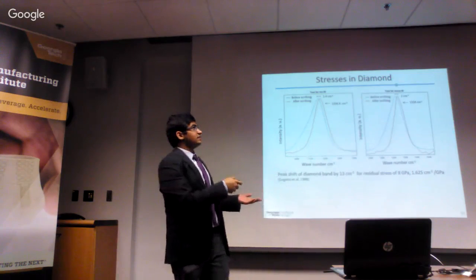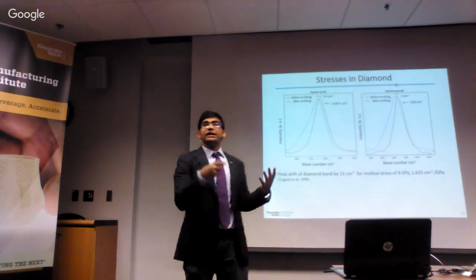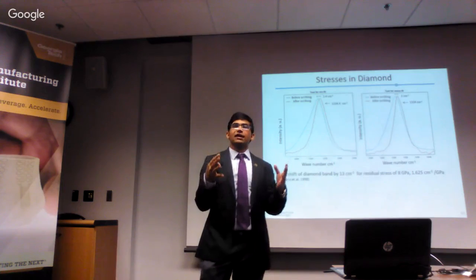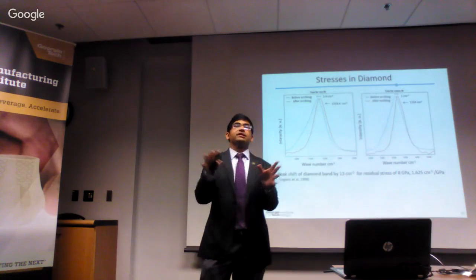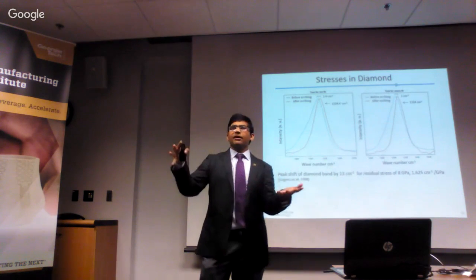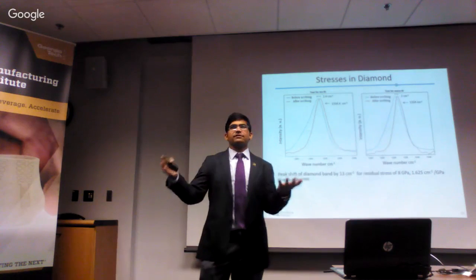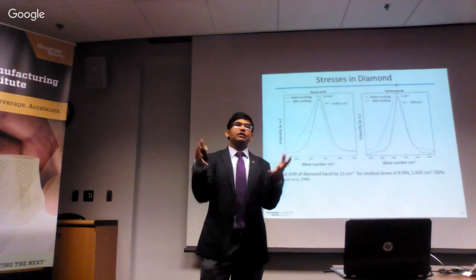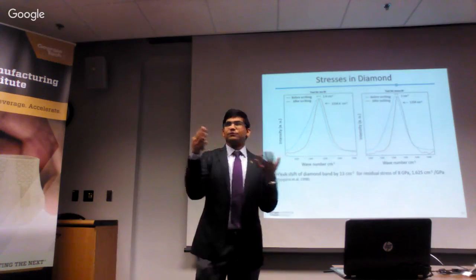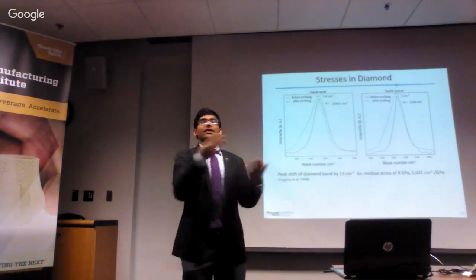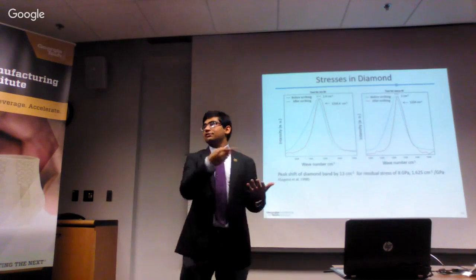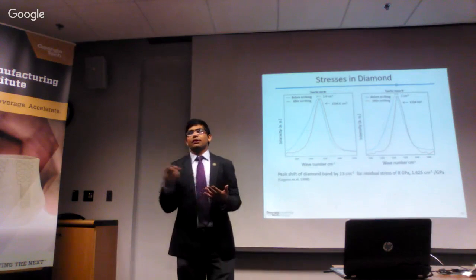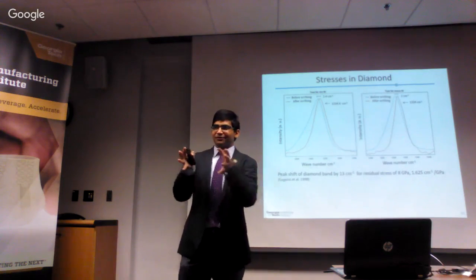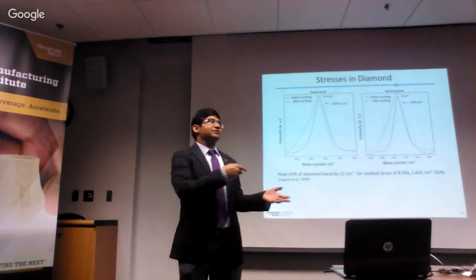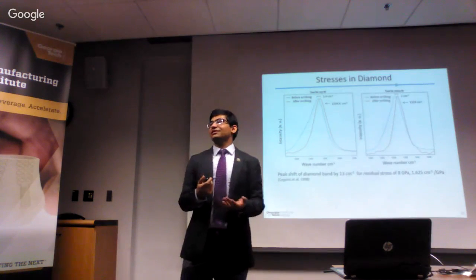The fact that we are seeing a peak shift here indicates that the stresses are large enough to create some plastic deformation, and the material doesn't come back to the same phase or structure as before. So there is some lattice deformation taking place, and that's why we see the residual stresses by the peak shift. If there were no residual stresses or no lattice being deformed, we would not have seen the peak shift.